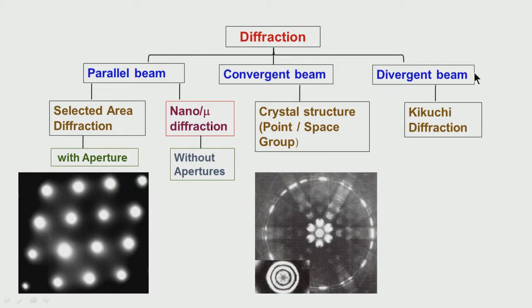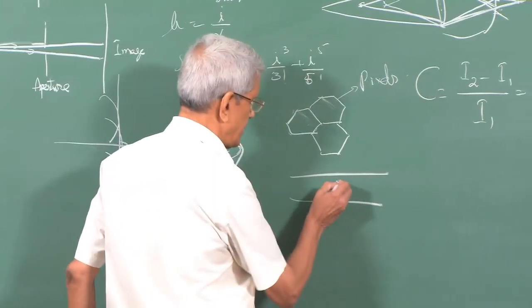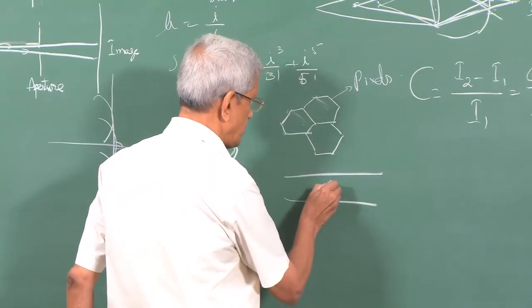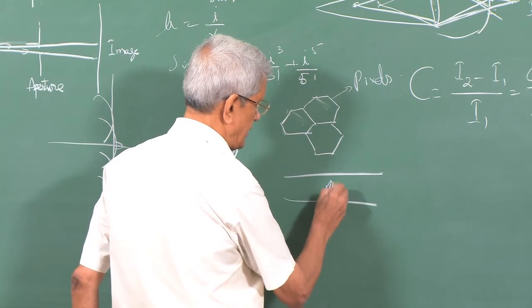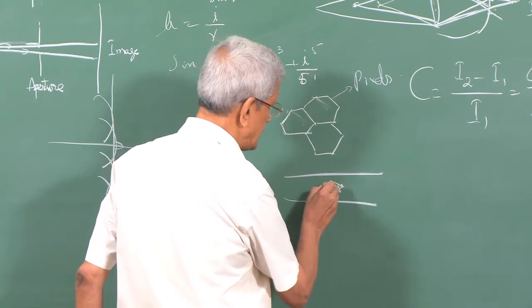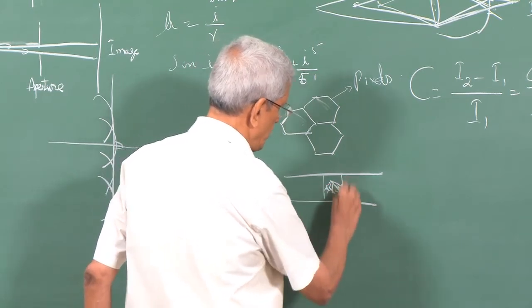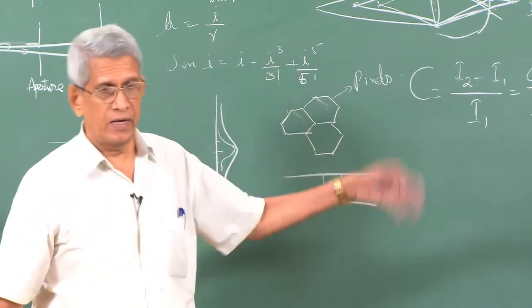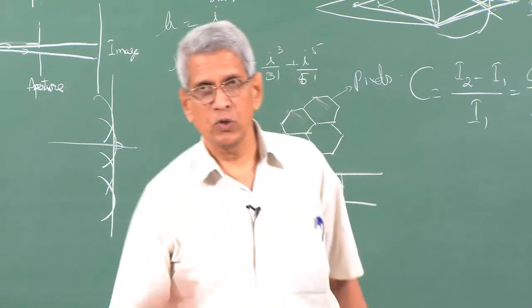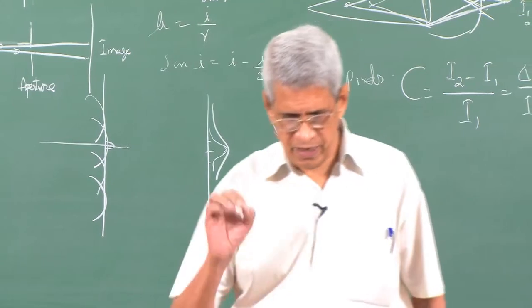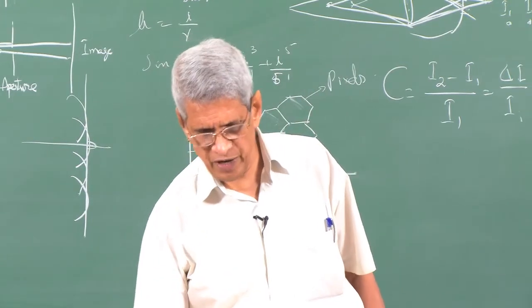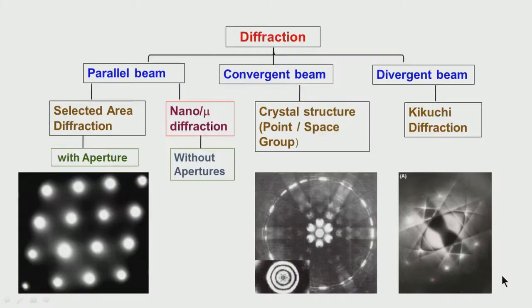The divergent beam is when the beam falls onto the sample and scattering takes place, inelastic scattering from a specific point. That is, the beam has lost some energy due to plasmon oscillations. So from this region, the beam is scattered in various directions. This beam could be diffracted by the planes, so it's a divergent beam which gets diffracted. This pattern, we call a Kikuchi diffraction pattern. This is how it looks like.